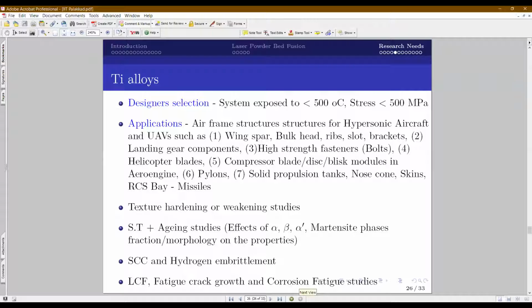Titanium alloys are strengthened, or the properties are tweaked, through solution treatment and aging, which involves formation of different sizes, morphologies and fractions of alpha or beta phase or the martensite phase. In the as-printed state, what I understand is we mostly see martensite phases, and the conventional solution treatment and aging may not work for the 3D printed one. There is a lot of scope for researchers to understand the heat treatment effects, mainly solution treatment, aging or annealing treatments, on the 3D printed titanium alloy, and you can tailor a specific heat treatment which gives the most optimized properties. This is an expectation from our industries. Currently few standards are available, but I am sure there is a gray area which can be easily attacked by our academic researchers to come out with a novel heat treatment scheme for the 3D printed titanium alloys.